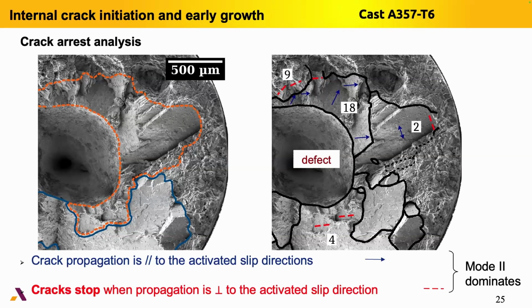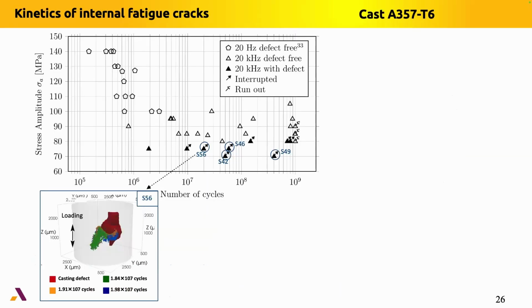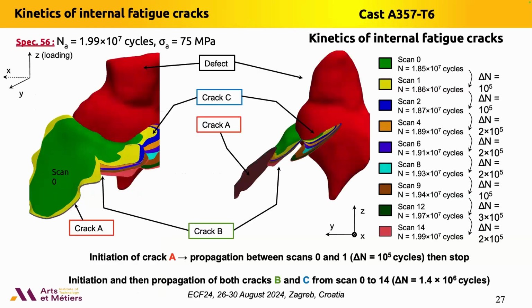That is classic in literature for surface cracks also, because we know that the initiation and the early crack propagation is done in shear, so in mode 2. So now, let me focus on the other specimen, number 56, which was loaded at 75 megapascal. For this specimen, we have the complete loading history, and it is very useful in order to reconstruct the crack growth kinetics.